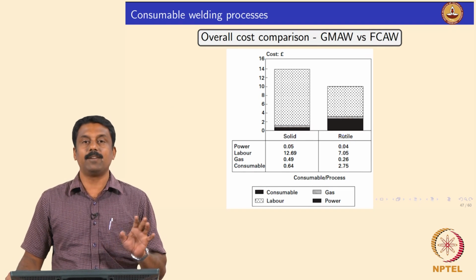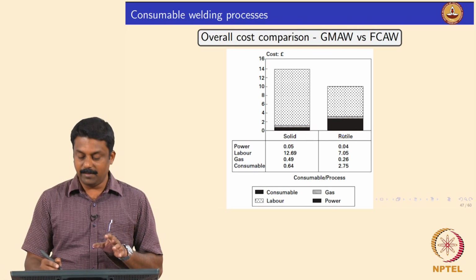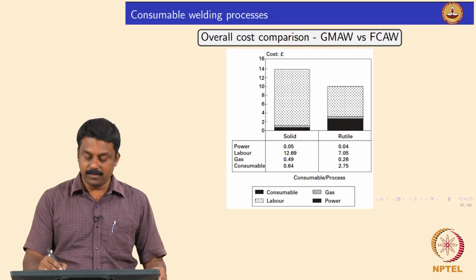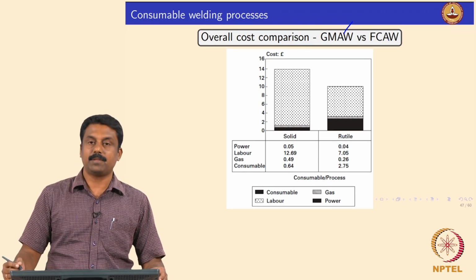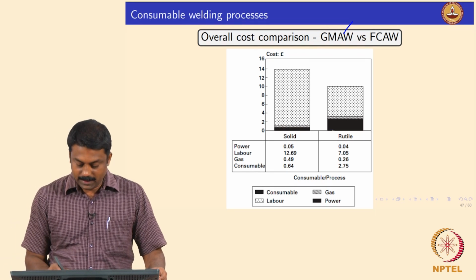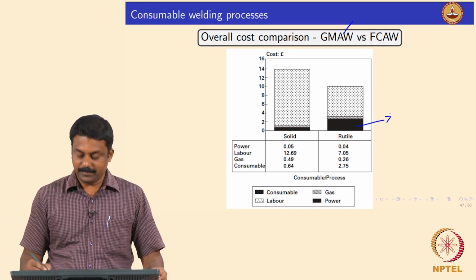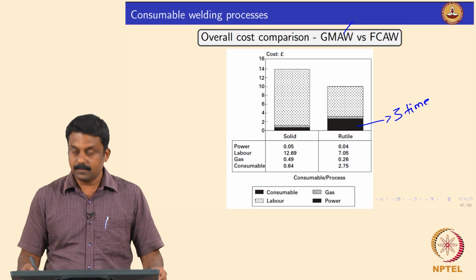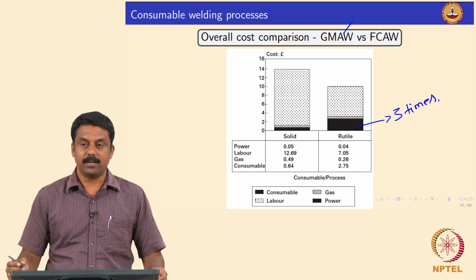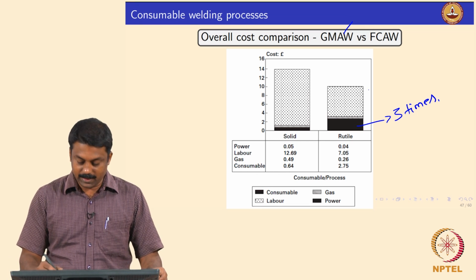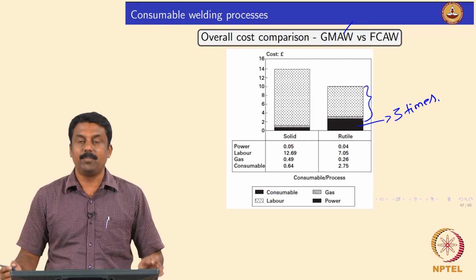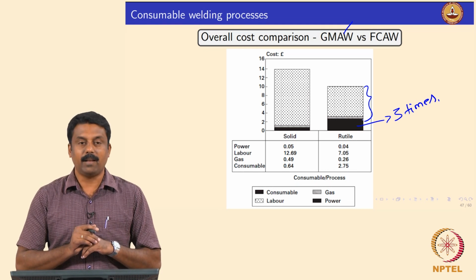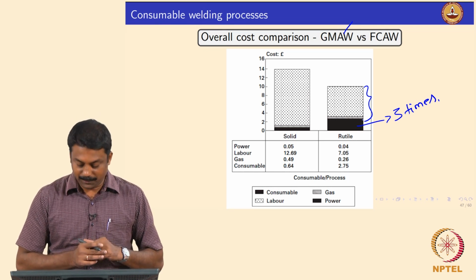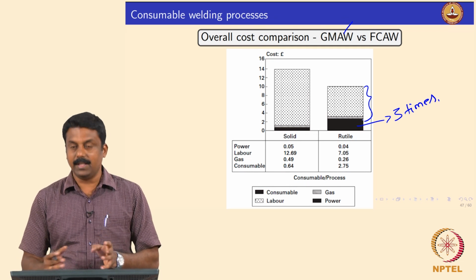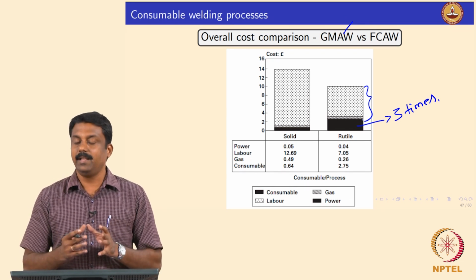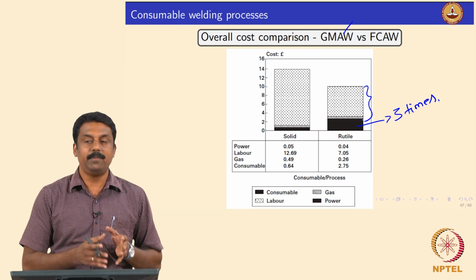For example, if you look at the overall cost comparison between GMAW and FCAW, GMAW is gas metal arc welding and this is flux cored arc welding. The consumable is always 3 times higher in the flux cored arc welding or in SMAW, the cost, right. But you overcome that by other factors. For example, you do not need shielding gas if you use self-shielded electrodes, right, or even if you use a rutile based electrode, the shielding gas necessary is much less than what you need for GMAW.